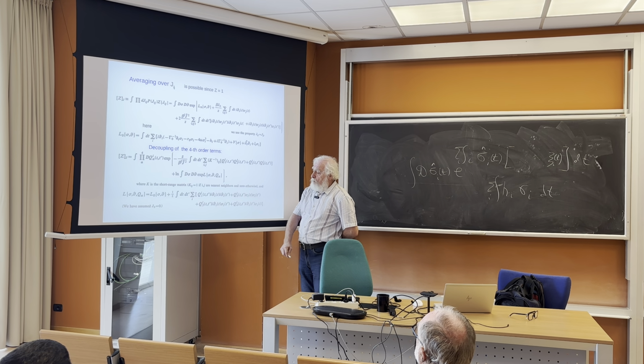So below some temperature, it freezes into a phase glass. Instead of the Ising order parameter, here we have an order parameter like exponent e to the i phi_xy. And one of the simplest observables for such a system is the diamagnetic response of this array, which appears if we change magnetic field below the glass transition.